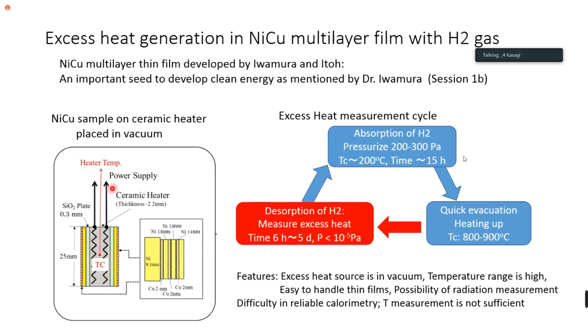We have a ceramic heater, and two samples on the ceramic heater, and we put the samples in the vacuum. The excess heat measurement cycle is something like this. First, in the absorption of hydrogen stage, it is pressurized with 200 to 300 Pascal and temperature like this. And then after 15 hours, we quickly evacuate the system.